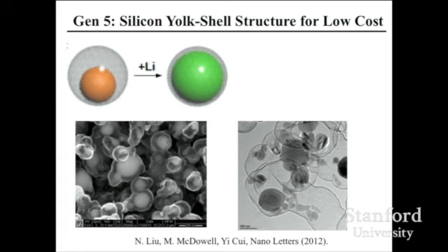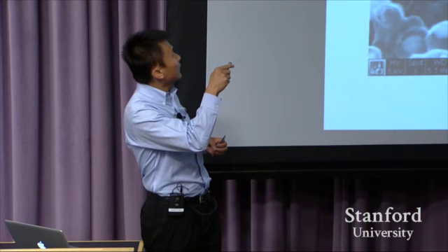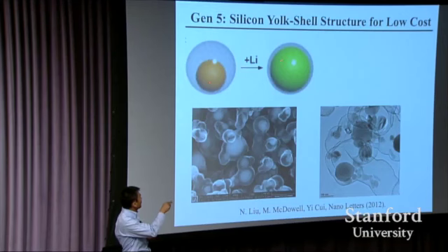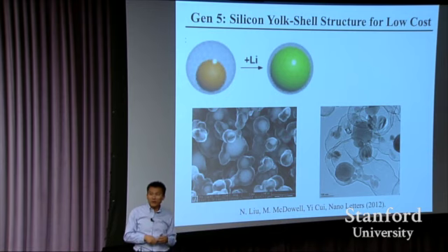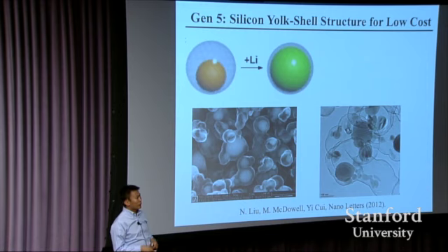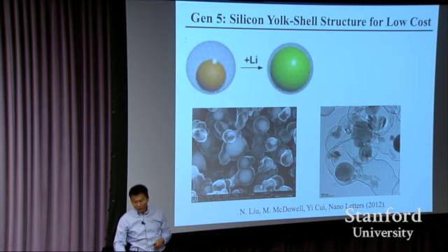This is a beautiful thing in nanoscience. Now you can make almost anything, any shape, any combination you like through smart synthesis. You can engineer empty space right here exactly right. Lithium comes in, silicon expands, it just exactly fits without cracking your coating. And then the electrolyte is sitting outside, so it doesn't see what's going on inside. This is the yolk-shell structure, silicon nanoparticle with a carbon shell right there.